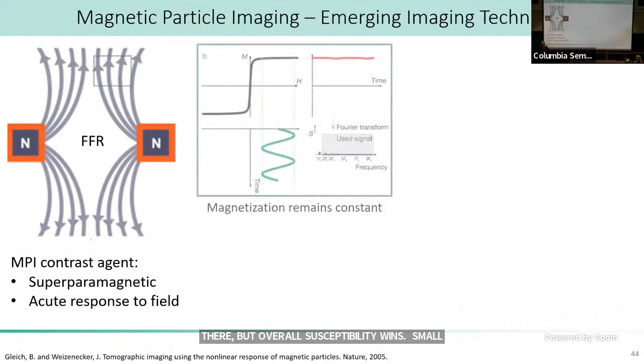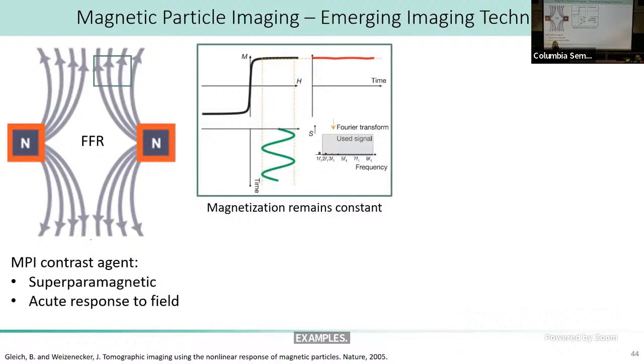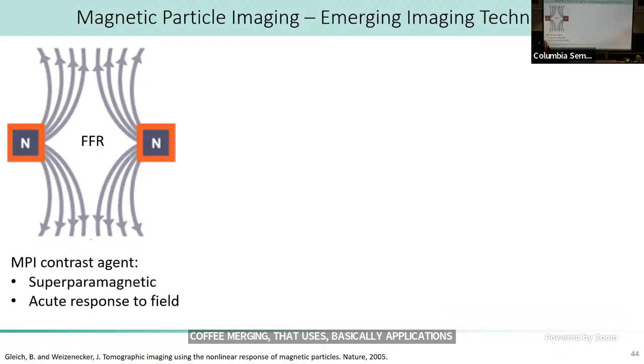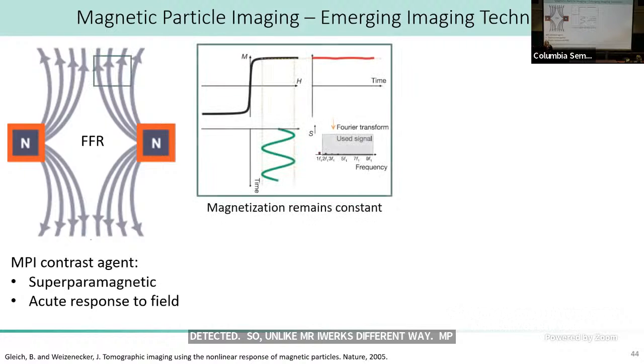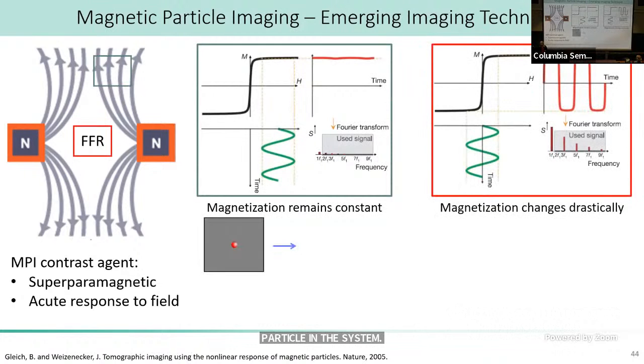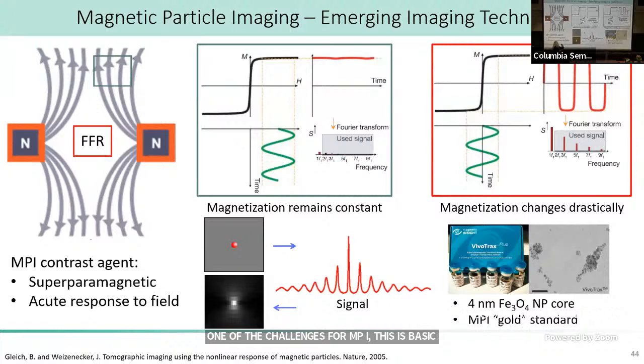Another really interesting case is whether we can use them for magnetic particle imaging. So I don't know if you've heard of MPI, but it's a background-free technique for imaging that's kind of emerging, that uses basically application of a magnetic field. And if you have something that's magnetized in the middle of it, it creates sort of a dimple in the applied field, which can be detected. So unlike MRI, which works in a very different way, MPI is really detecting the actual iron oxide or magnetic particle in the system. And one of the challenges for MPI, and this is just some of the basic information about it, is that you don't really have very good agents that give a big enough change in magnetization for the field strengths that they're operating at. So they also depend on susceptibility.